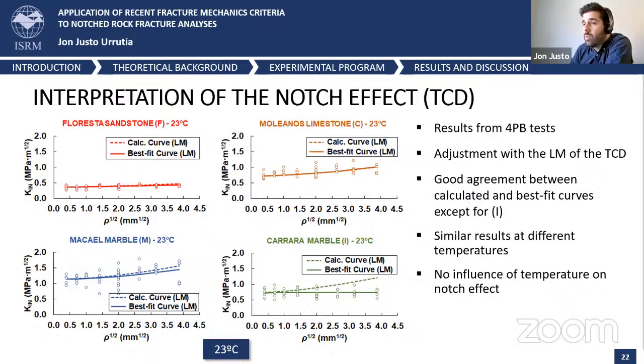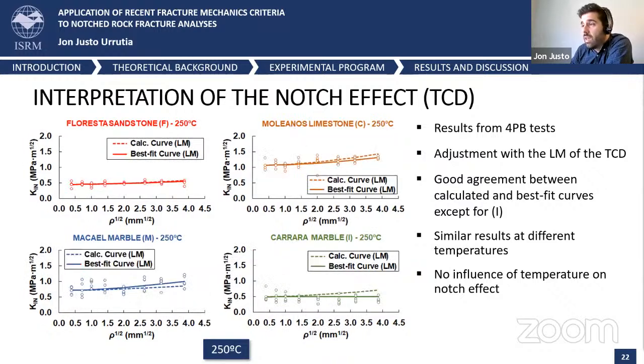We can see a good agreement between both of the curves. Similar results are obtained also at higher temperatures. These are the results for 250 Celsius degrees. And we can observe that the trends are kept roughly the same, which indicates that there is no strong influence of temperature on the notch effect.